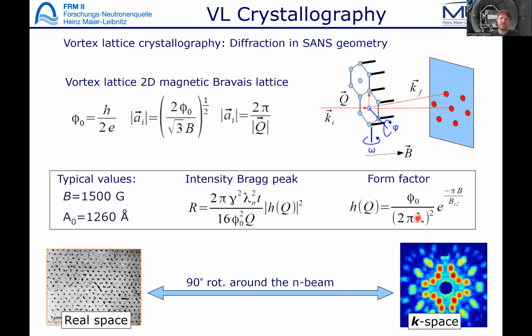So what we see here on the detector, if we do a rocking scan, where we rotate the sample and therefore rotate the reciprocal lattice through the Ewald sphere, and then sum up, is a very nice picture in reciprocal space of our vortex lattice, which directly gives you the symmetry of your vortex lattice in your bulk crystal. And as the vortex lattice is a 2D lattice, this is just a rotation of 90 degrees around the beam axis to go to the real space lattice, to get the symmetry of your real space lattice.